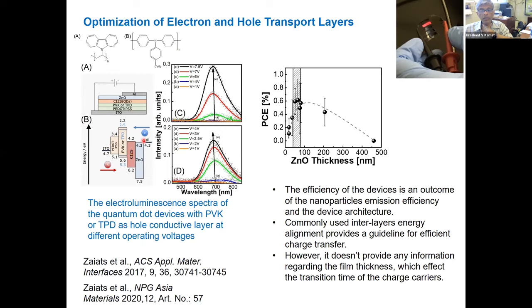And what we did was we varied the thickness of zinc oxide to see how the efficiency changes. Again, these are the LED response at different voltages of these cells with these two different hole transport layers. But what is interesting in this slide is the zinc oxide thickness. As you can see here, there is an optimal thickness at which the electrons and holes come together, very thin. So as you increase the thickness, it takes much longer for electrons to come in. As a result, you drop in your efficiency in the cells.